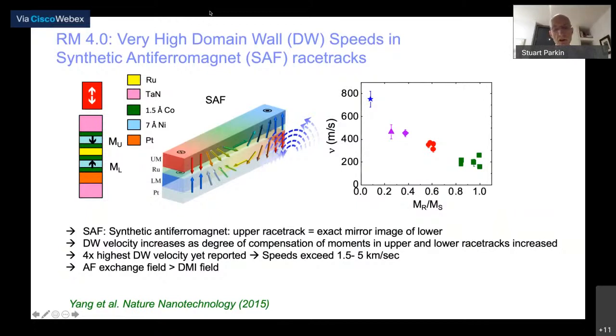And it turns out, again without going into any details, what makes racetrack really exciting today is this concept of using a synthetic antiferromagnetic racetrack. In spintronics, a key to developing nanoelectronic devices is controlling the long-range magnetic dipole fields from magnetization. Otherwise, there's interaction between neighboring magnetic bits in magnetic random access memory, for example, or in racetrack, domain walls will interact with one another. You have to eliminate the magnetization. And so a concept that I actually invented 25 years ago, and which was used and is still used today in magnetic recording read heads, is something I call a synthetic antiferromagnet.